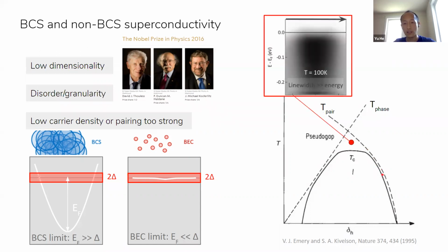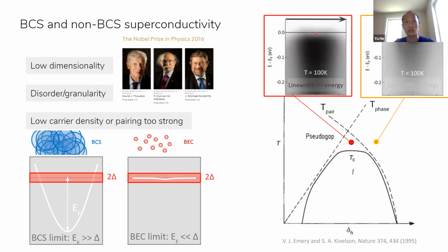And with that understanding, we flip to these photoemission measured spectra near the antinode, where the superconducting gap is supposed to be the largest, in the normal state. And we see that indeed, at face value, above Tc near optimal doping, there is some kind of spectral gap already, while in a sufficiently overdoped sample in the normal state, there is no spectral gap anymore.